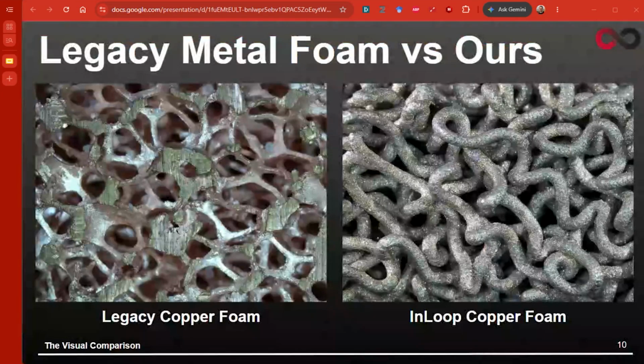So looking a bit closer at the microstructure level here, here's what legacy copper foams look like compared to InLoop copper foam. To give a little background on how legacy is being manufactured relative to us, they use what's known as a syntactic process, which is functionally where you take a big vat and you fill it with a bunch of sacrificial ceramic spheres. And then you pour the liquid metal over those spheres to fill in all the gaps in between, let that metal cool, and then you dissolve out those spheres, leaving behind this network of spherical voids and cells that are connected by these straight links.